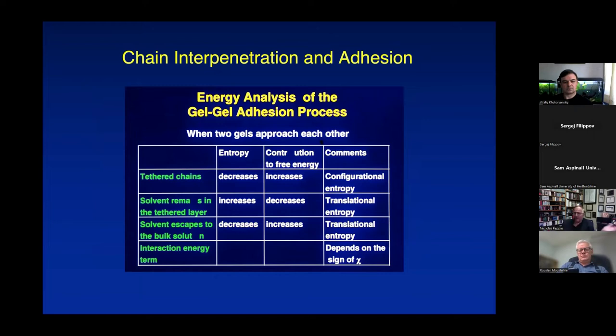Why? Because they change the configurational entropy. Is the entropy increasing? No, it decreases. What about the contribution to the free energy? It's increased. What about the solvent that is around the tether chains? Well, the entropy will increase because of the solvent. You can imagine that.